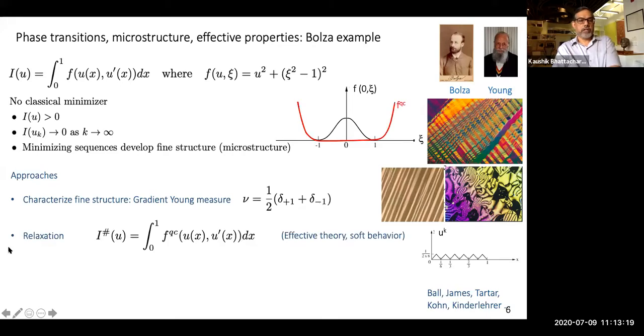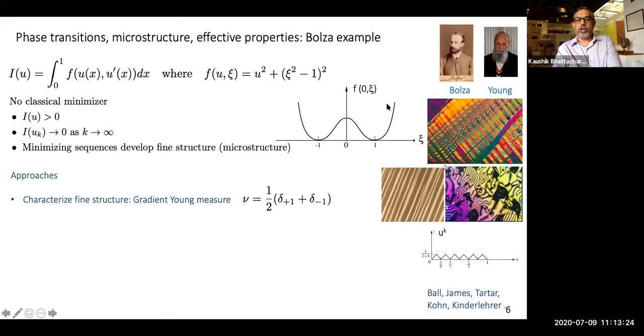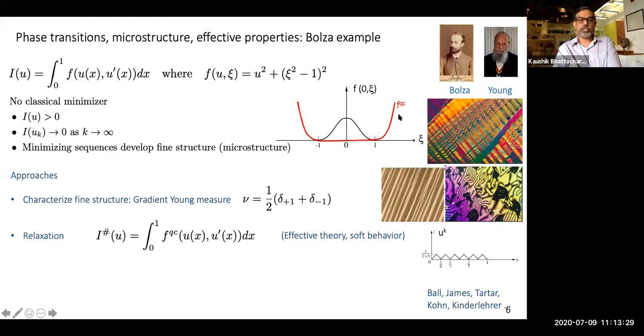The second, you can study the relaxation. So this was your original non-convex energy, but after forming microstructure, the behavior is guided by this red curve. So we'll call this the relaxed energy or the quasi-convexification. And you see that this has a large region where the energy is flat. So this is a region where you can very quickly change behavior. So you see that relaxed energies typically have a lot of soft behavior, even though the underlying material itself is hard.